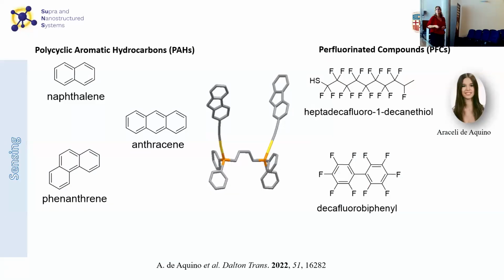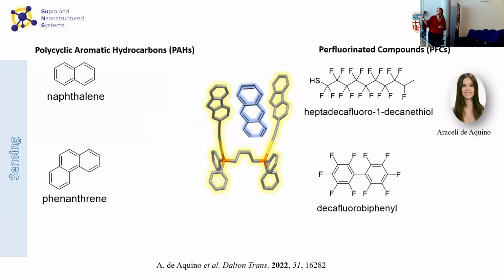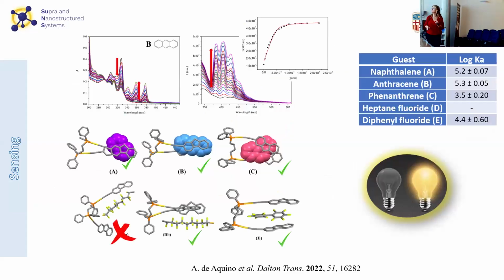So in these cases, what Araceli did was synthesizing this gold compound, having this pincer structure, and putting it in contact with different contaminants, let's say. And the idea is trying to see if, when the contaminant is within the tweezer, it can induce some changes in the luminescent properties. So this is a sensor. And why is it important to use luminescence? Because luminescence is very sensitive. So you can really detect very, very small amounts of samples. So this was the interest in this field.